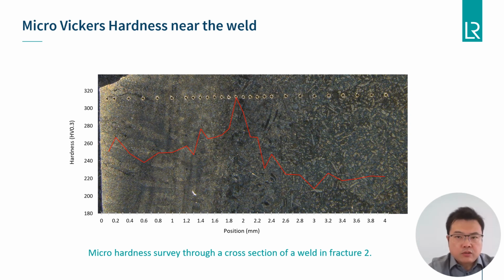The picture clearly shows that the hardest region was found in the heat-affected zone, and the hardness values changed from about 300 to around 200 over a very short distance during the transition from the heat-affected zone to the original propeller microstructure. The sharp change in hardness can initiate fractures due to accumulated slip stresses and the inherent brittleness of the harder microstructure. During operation of the propeller, the cyclic forces applied to the blades have clearly promoted the propagation of the fatigue fracture originating from the vulnerable microstructure within the heat-affected zone.